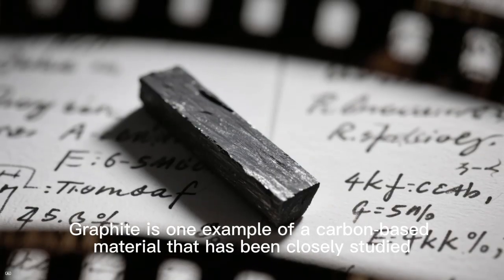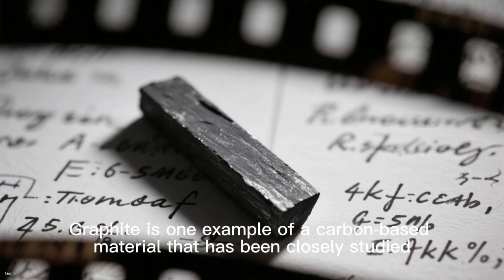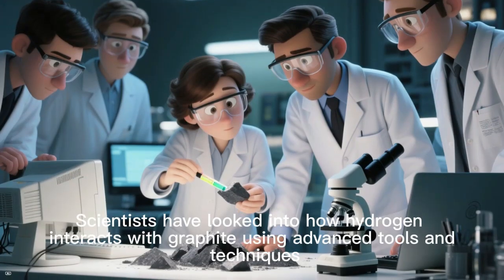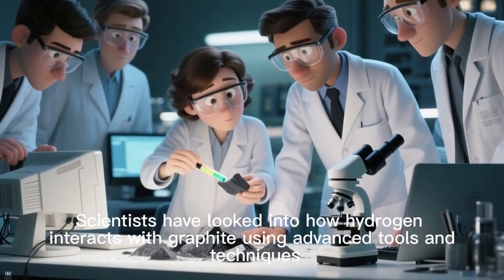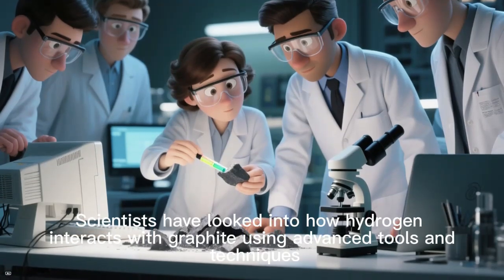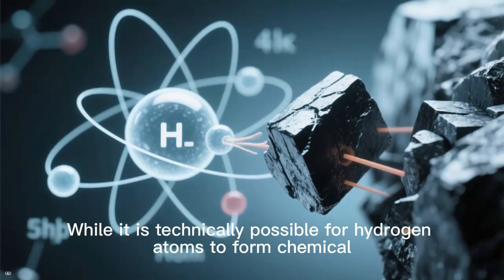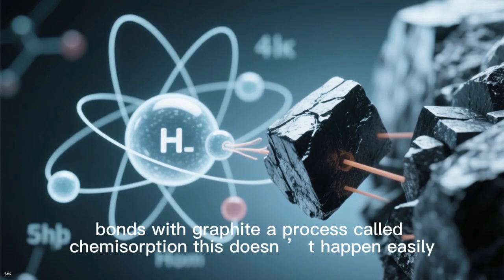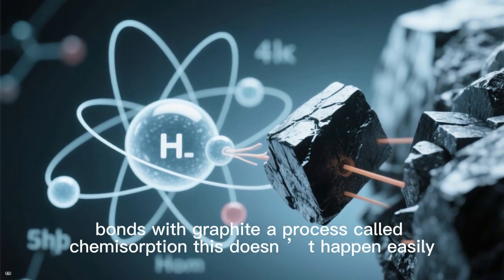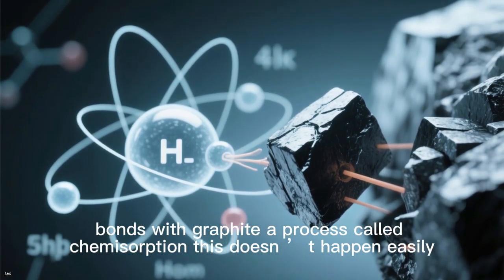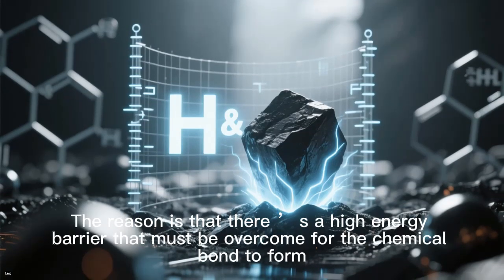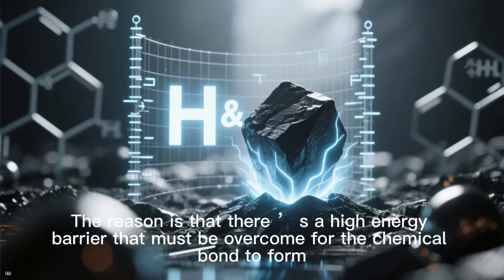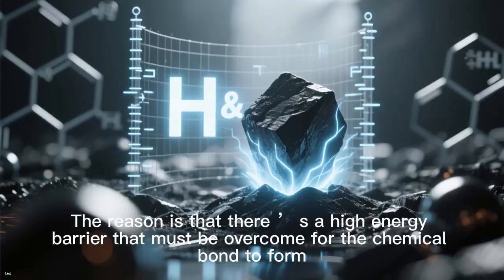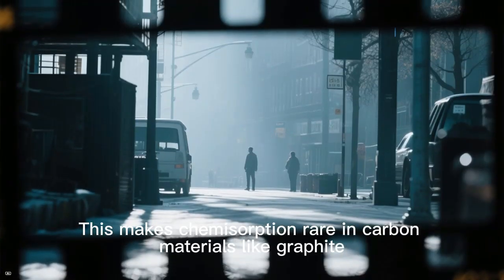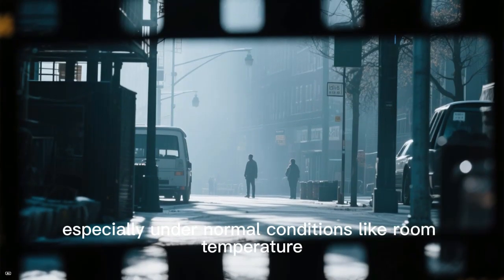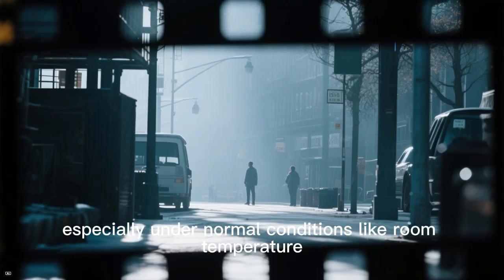Graphite is one example of a carbon-based material that has been closely studied. Scientists have looked into how hydrogen interacts with graphite using advanced tools and techniques. While it is technically possible for hydrogen atoms to form chemical bonds with graphite, a process called chemisorption, this doesn't happen easily. The reason is that there is a high energy barrier that must be overcome for the chemical bond to form. This makes chemisorption rare in carbon materials like graphite, especially under normal conditions like room temperature.